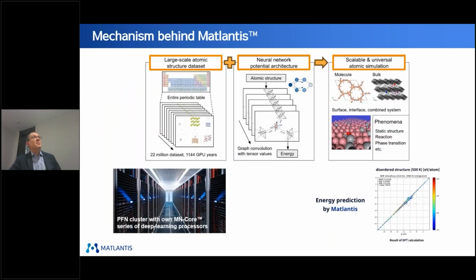The mechanism behind Matlantis is like this. Matlantis is based on a very large-scale atomic structure data set, more than 22 million data sets, equaling more than 1,000 GPU years that have been spent on our own supercomputing cluster and the PFN cluster. And this is connected to our own neural network potential architecture. This provides what you achieve when you use Matlantis, which means that you can predict energies and atomic positions very accurately.